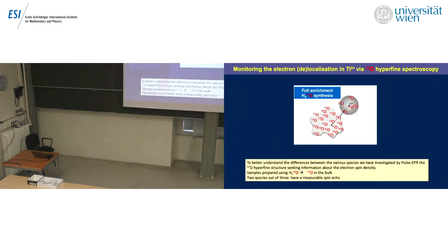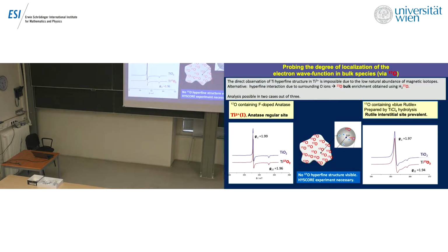And so we have to rely on 2 systems only: the anatase system with the strange, now I can say, axial system, and the interstitial site of rutile that can be increased in amount with a simple trick in the preparation. In this case, we can record the spectra. If you do normal continuous wave EPR, you see that there is absolutely no difference between the 2 spectra. So it seems pretty useless to put oxygen-17 in the system. But if you do pulsed EPR, there is a difference because there are very tiny interactions.